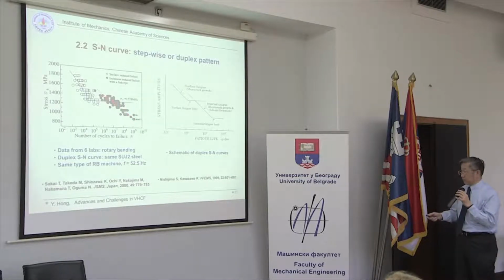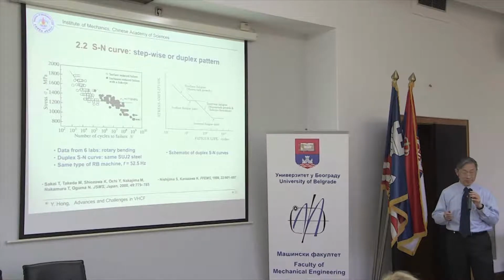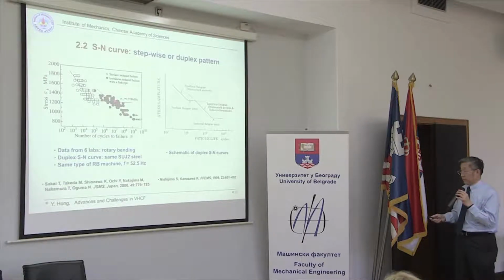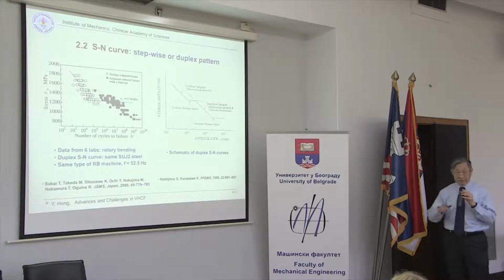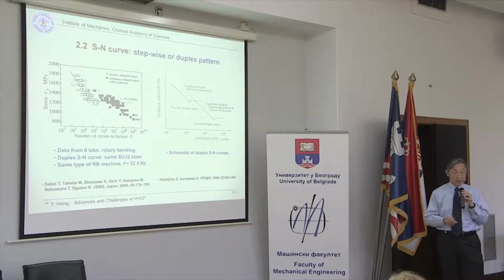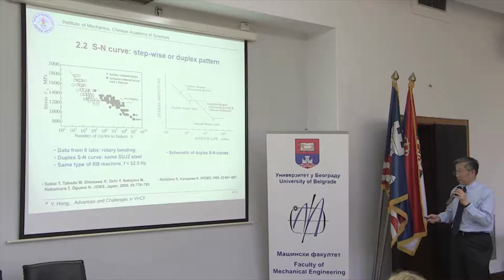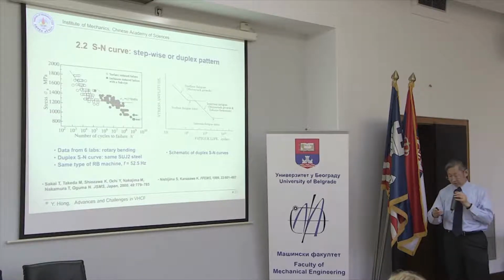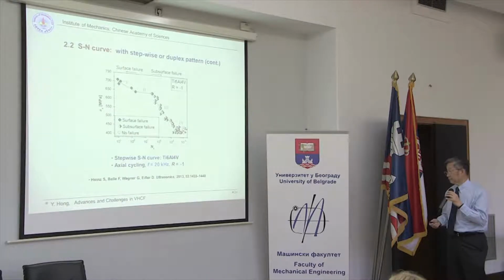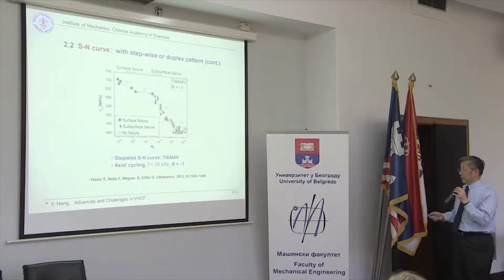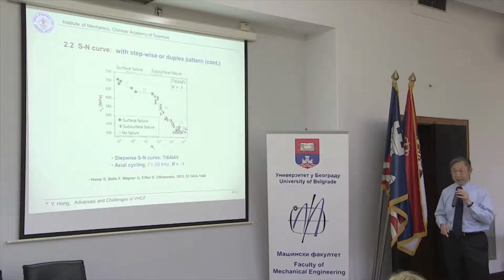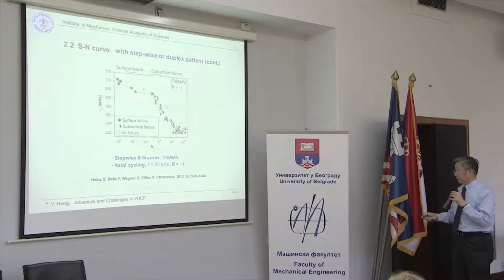This experimental result and this schematic show this. And it is very likely that this type of S-N curve is due to the different mechanisms of crack initiation. The first part is due to surface crack initiation, and the second part is due to internal crack initiation. And this is the case for high-strength titanium alloy. The previous one is from high-strength steel, and also shows different parts of the S-N curve.